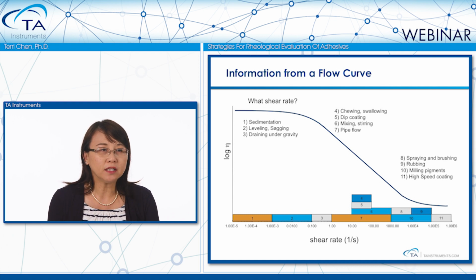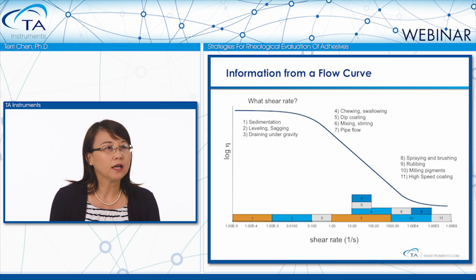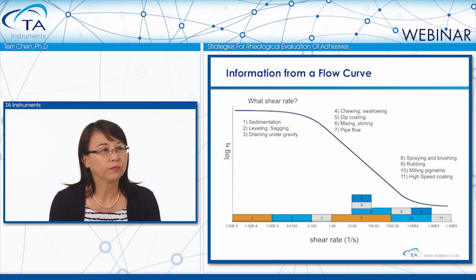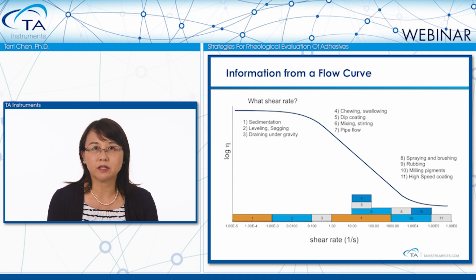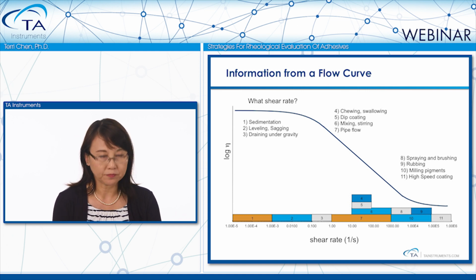Viscosity measured at medium shear correlates to a liquid sample mixing and transportation, such as pumping or pipe flow. The high shear viscosity measurement directly correlates to the coating applications conditions.